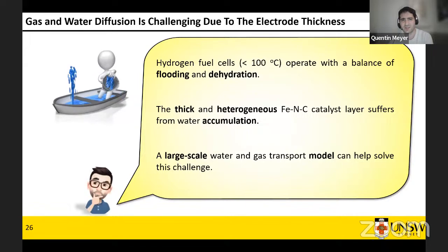So an interesting thing that was a bit the drive for this is that this kind of iron-nitrogen-carbon catalyst layer suffers from water accumulation because they're very, very thick with some cracks. So what we wanted to have is a large-scale water and gas transport model to actually figure out what's happening and solve it.